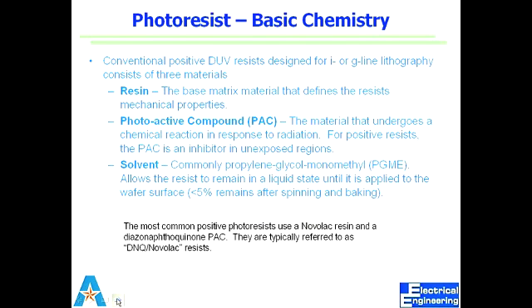So you'll see this DNQ Novolac over and over. It's nothing but short for a resin called Novolac and a PAC called DNQ. Right? So Novolac PAC is a type of resist. Solvent is what gives it a liquid state until we get there. But once we spin it and bake it, there is some of that left behind, but it's less than 5%. We can still live with it. We get rid of that once we do baking. Once we do hard bake, then we get rid of all solvent.